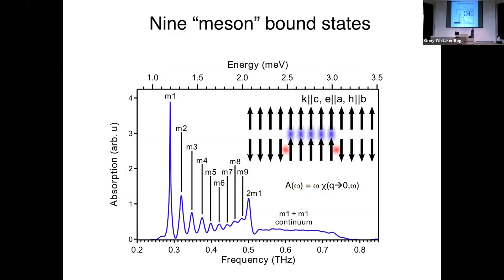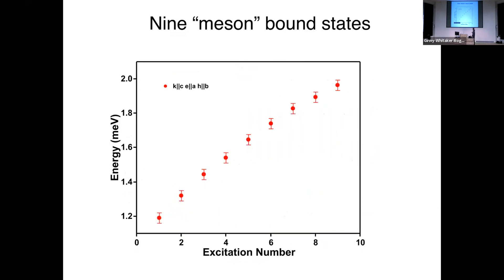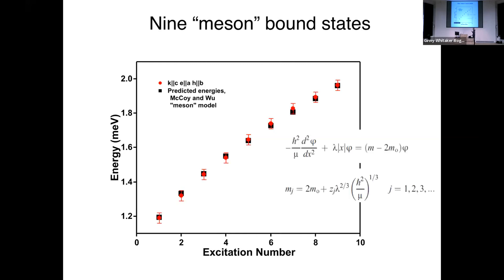Looking at just the lowest peaks in the lowest temperature data, we label them M1 through M9. We can plot their energies versus an index M1, M2, M3, M4 up to M9, and the McCoy-Wu model from 1978 — based on the Airy function solutions — fits the entire discrete spectrum with just two or three parameters. This is a quite remarkable convergence of theory and experiment, many years later.